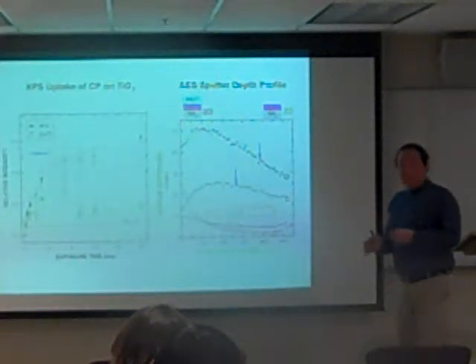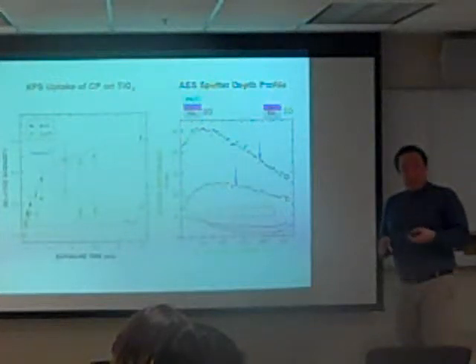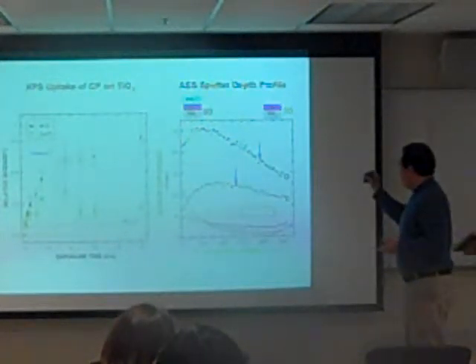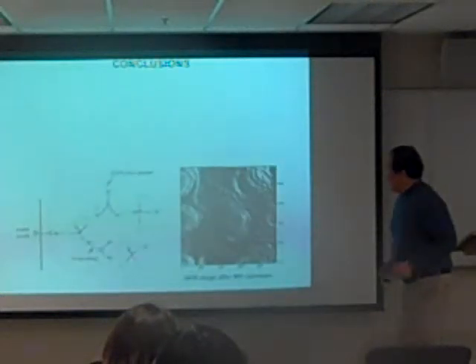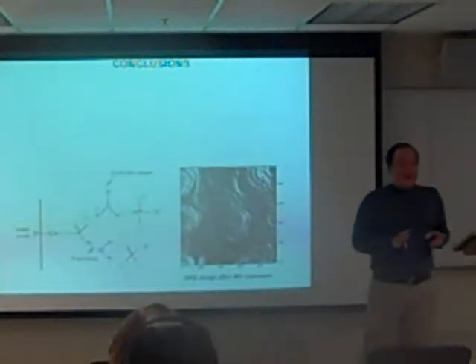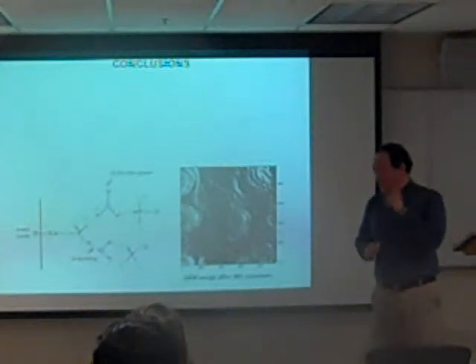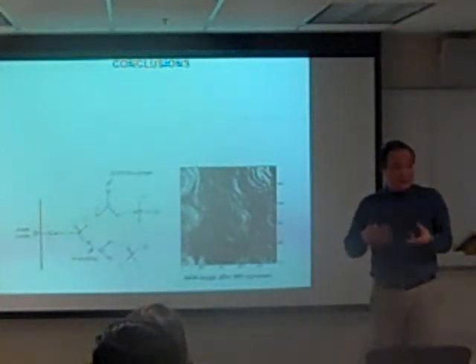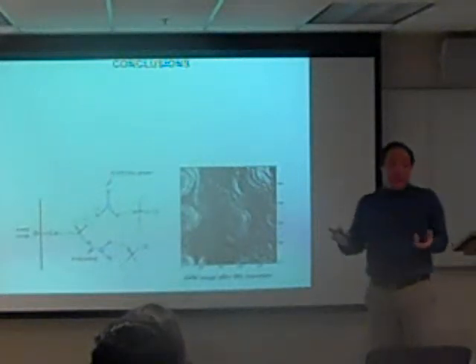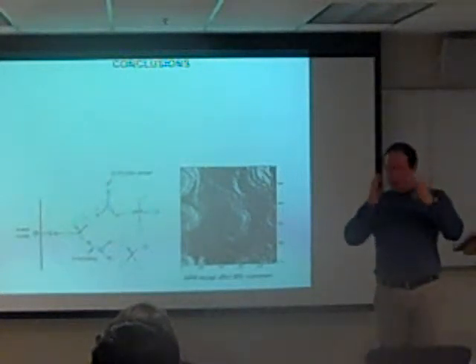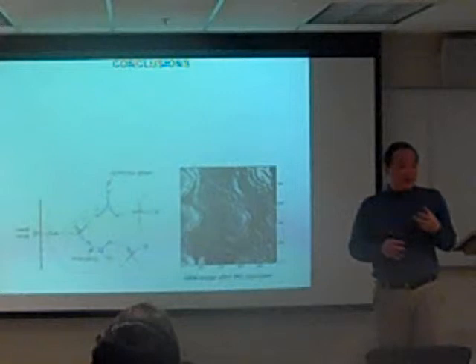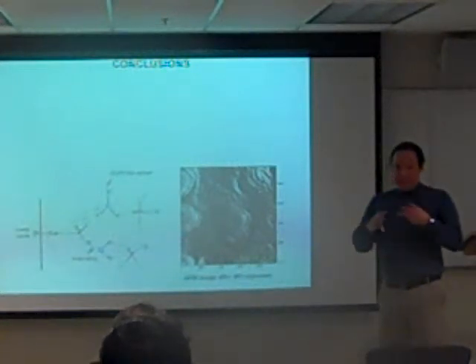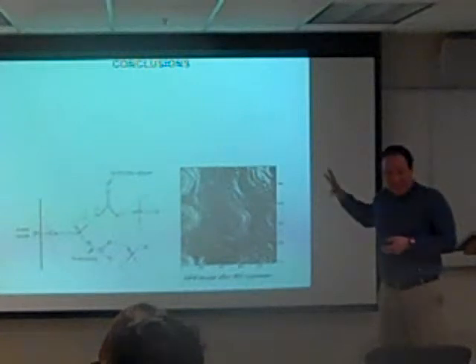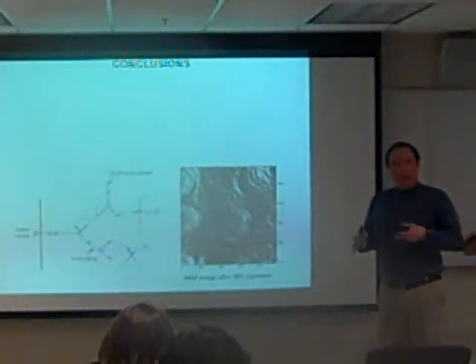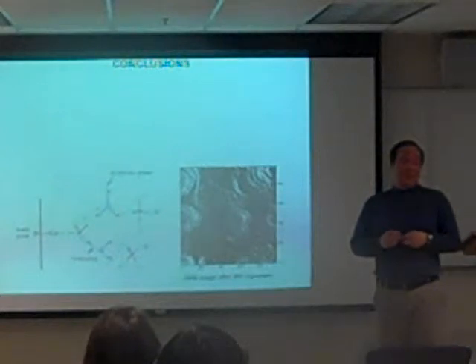So the overall picture in terms of adsorption on TiO2 is basically evidence for islands. Now, one question that you may ask is, you can't have negatively charged groups that just grow on the surface. What's the charge balance? That's a good question. If it's not calcium, what is it? The only thing we can think of, as far as postulating, is the hydronium ion that may serve as the charge balance. But anyway, that's a very interesting question, and I don't know, it may or may not be convincing, but that's the best explanation that we can think of.